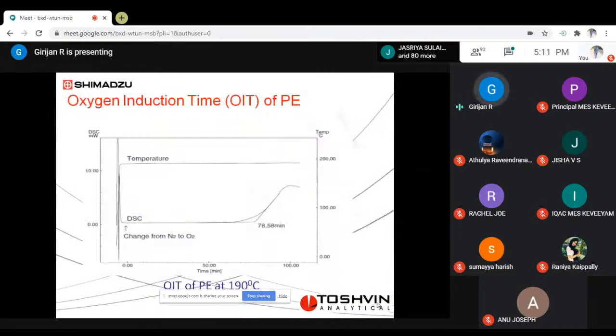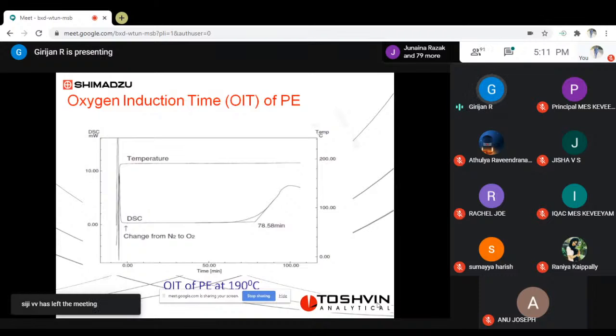I'll just show you two examples before I finish. Oxygen induction time of polyethylene. See, we heated up to 190 degrees centigrade in a nitrogen blanket. At exactly 190 degrees centigrade, we introduced oxygen into the system in place of nitrogen and continued heating. And then what happens? After around 78 minutes, an exothermic peak starts coming out. That means it has started undergoing oxidation. So for this PE film to undergo oxidation, it has taken 78 minutes. And that is what is called the oxygen induction time: after introducing oxygen, how much time it takes for the polymer to undergo oxidation.